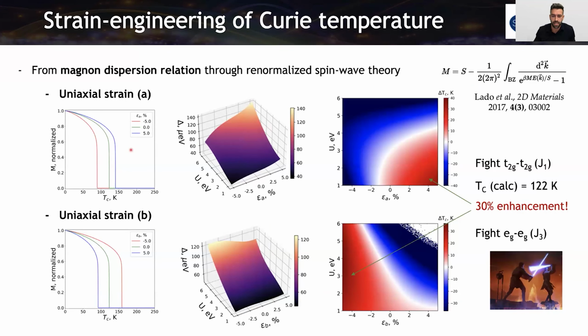Then from the magnon dispersion relation, applying spin wave theory, we can calculate the magnetization. We predicted 122 K, and the experimental value is around 150, so it's quite close. And we observed this enhancement of the Curie temperature.